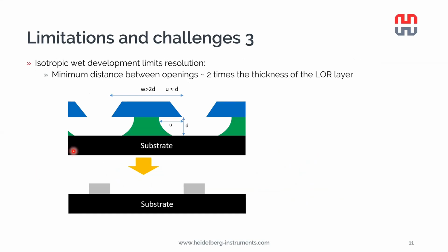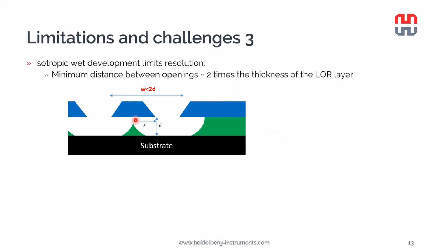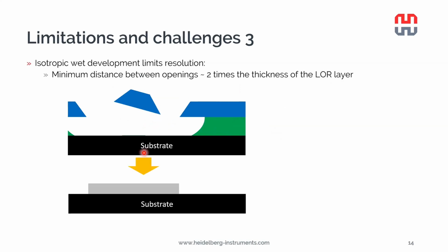This is due to the fact that the isotropic development is actually determining the minimum distance between the openings in the PPA. And this is approximately 2 times the thickness of the LOR layer. It's explained best by this simple animation here. As you can see, as we bring the openings in the PPA closer to each other, eventually the undercuts reach each other, and the PPA on top becomes freestanding, and it will fly away in the developer. And we end up having just a continuous field of metal instead of our line and space pattern.